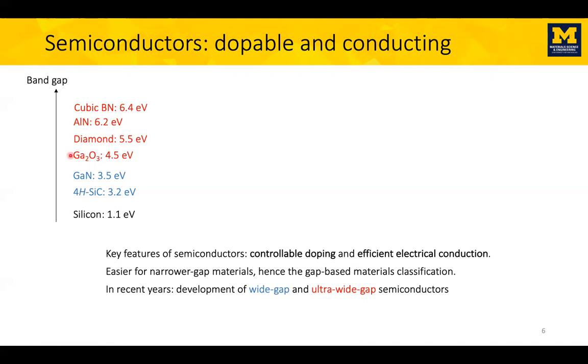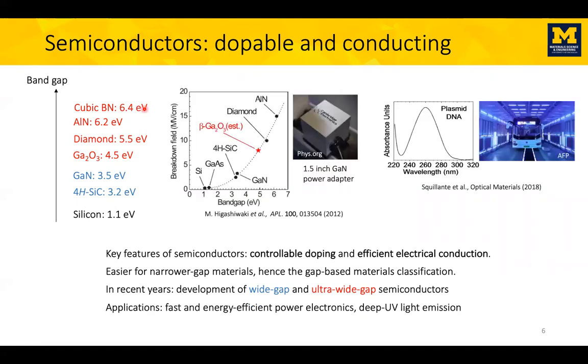I'll tell you more about gallium oxide with the band gaps of, you see them, they have gaps wider than the 3.5 eV of gallium nitride. As you see, the progress has been going towards wider and wider band gaps. What can you do with these materials? First of all, why do you want the band gap to be wide? The reason is the wider the band gap of the semiconductor, the stronger the electric field it can tolerate.